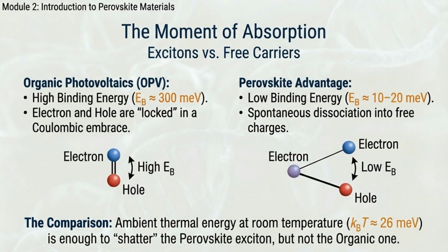Because the electron is negatively charged and the hole is positively charged, they naturally attract each other. In many materials, particularly in organic photovoltaics, or OPVs, this attraction is incredibly strong. The electron and hole become locked in what we call a Coulombic embrace, forming a tightly bound, neutral quasiparticle called an exciton. In organic solar cells, the binding energy holding this exciton together is massive, typically around 300 millielectron volts. As long as they are bound, they cannot generate electrical current. To rip them apart, device engineers are forced to create complex bulk heterojunction interfaces to physically strip the charges away from each other, which inherently costs voltage and efficiency.